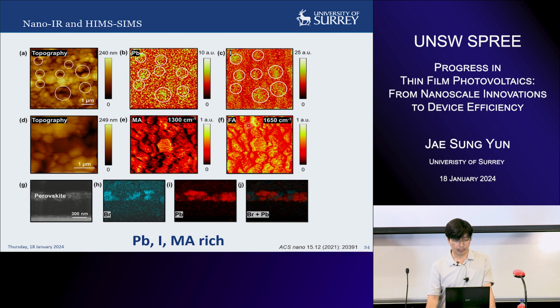We can see that they have more methyl ammonium compared to FA, the other A-site cation. And also we probed with TEM. We tried to measure whether such composition inhomogeneity only happens on the surface. So we checked the cross-section and performed EDX and found out that these grains are actually not just on the grain surface, but within the entire film thickness. So we found out that these grains are lead and iodine rich, as well as methyl ammonium rich.